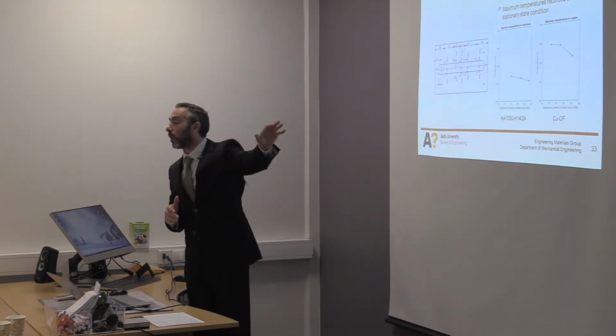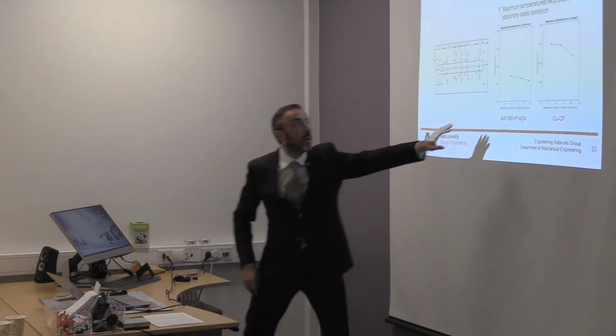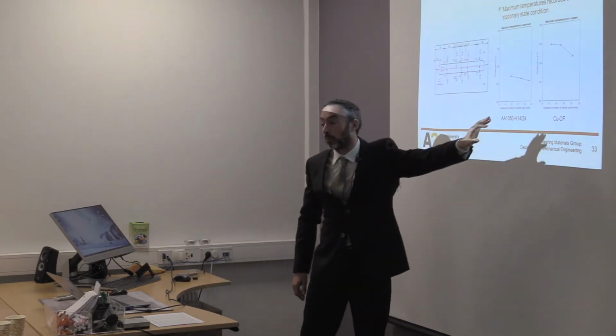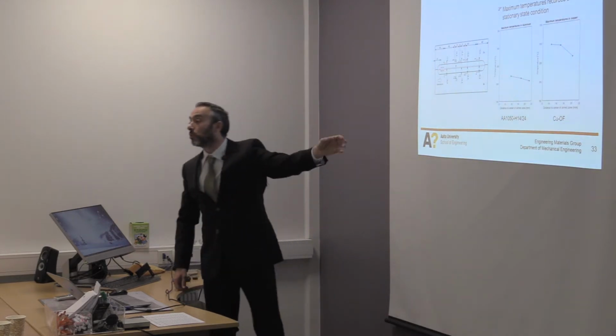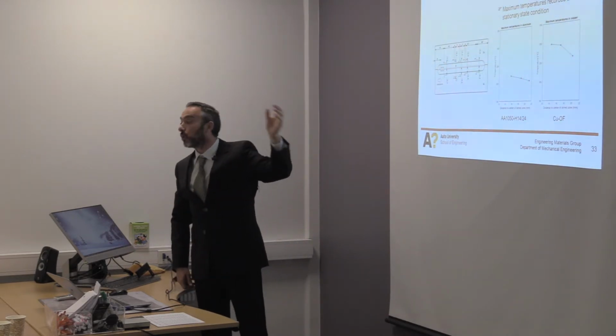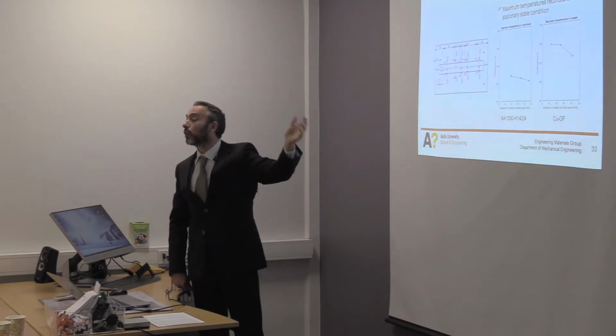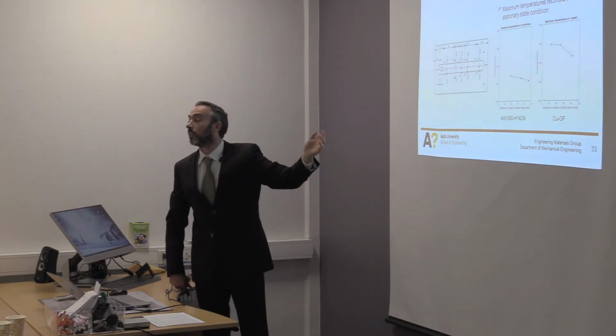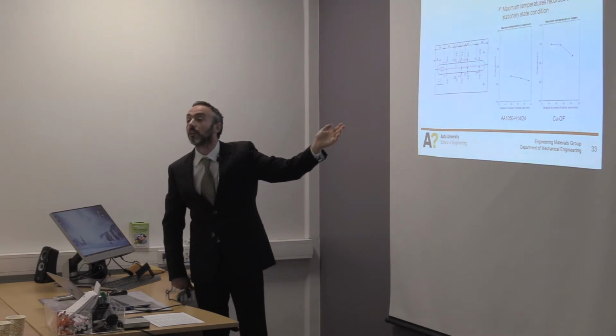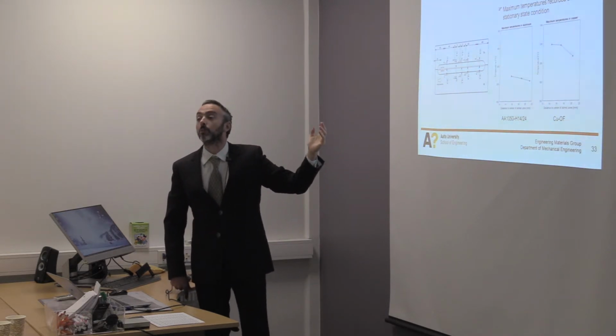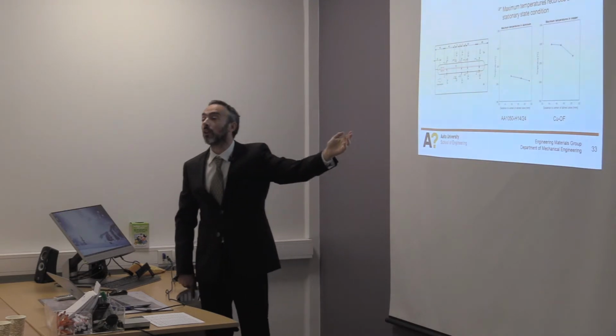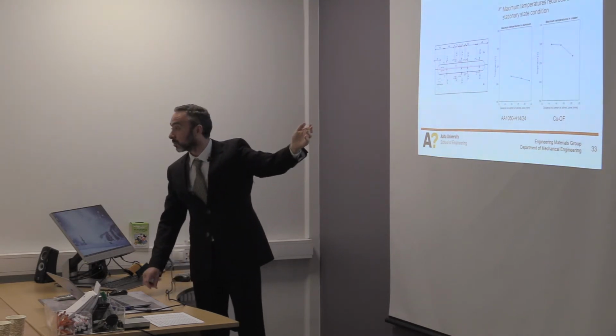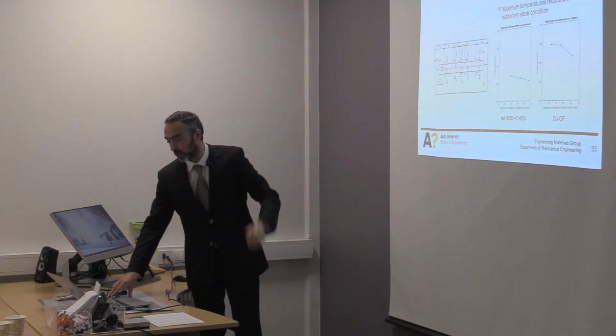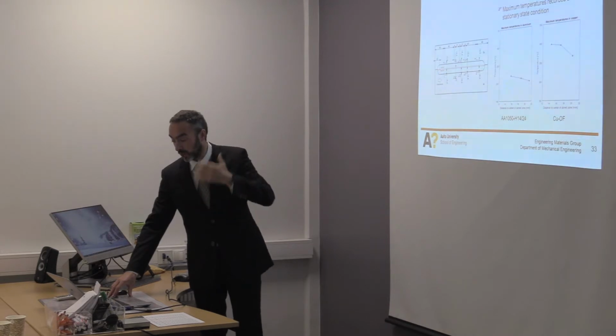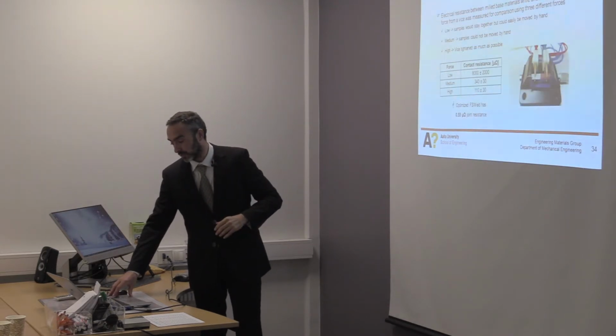And what you can see on the right side is that the temperature on the aluminium side is lower than in the copper. So the issue here is that the power source is the materials and not the friction, because most of the tool is over the aluminium, and if the friction was the source of the heat, then the aluminium would be hotter. Okay? But because of the higher internal energy of the copper, you have higher temperature. So this is an important issue. We have this friction word in the title, but it is the plastic deformation that generates the heat and the new chemically active surfaces.